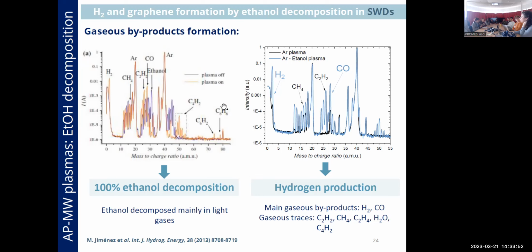What about the production of gases? Here in this graph, next to the previous one, we are comparing the gases coming from a pure argon plasma and an argon plasma with ethanol molecules. We can see that the mass spectrum is quite different. The black one is the gases from the argon plasma, and the blue one, argon-ethanol, is the gases from the argon-ethanol plasma. You can see that mass-to-charge ratio equal to 2, which belongs to the production of hydrogen, increases a lot. Actually, it is the one that increased the most.